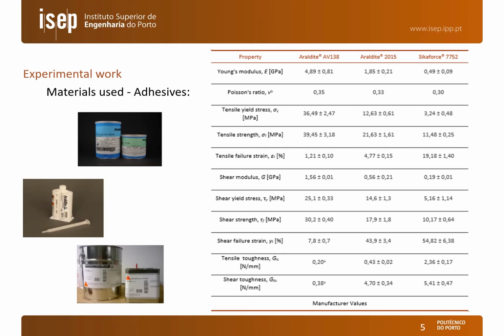The first one, the Araldite AV138, is a brittle adhesive. The 2015 is an adhesive with a smaller strength than the former one, but with a higher ductility. Both of these adhesives are epoxy-based. And finally, we are going to test the polyurethane Sikaforce 7752, which has a smaller strength than the Araldite adhesives, but it is much more ductile.